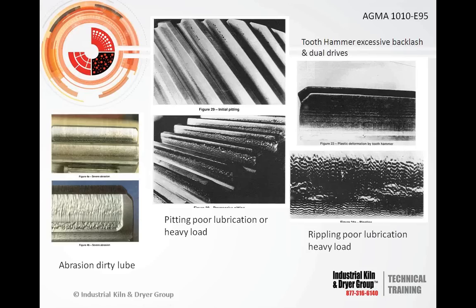I've seen that happen in several cases in the industry where a brand new gear can be worn out in less than a month. It's purely because there wasn't enough oil and it started to pit. Then you got all the contamination of that metal mixed in the oil and it lapped down the gear in a very short period of time.